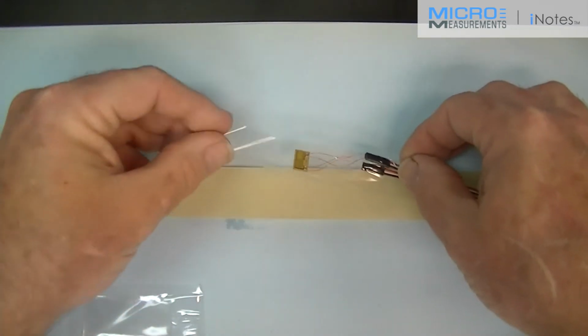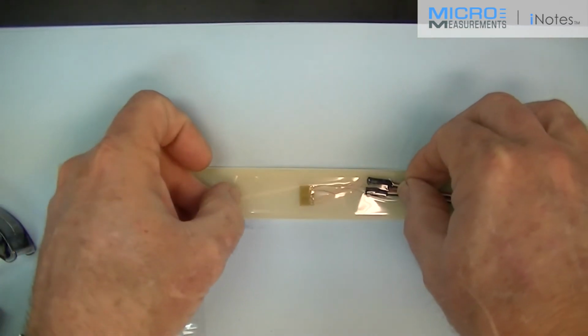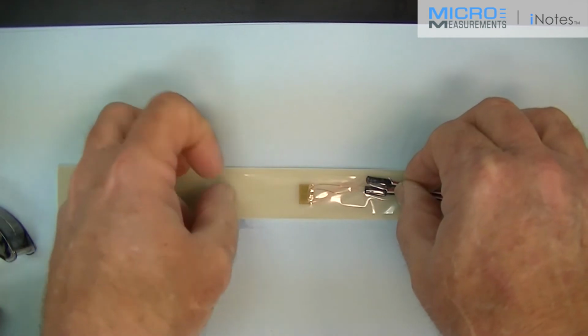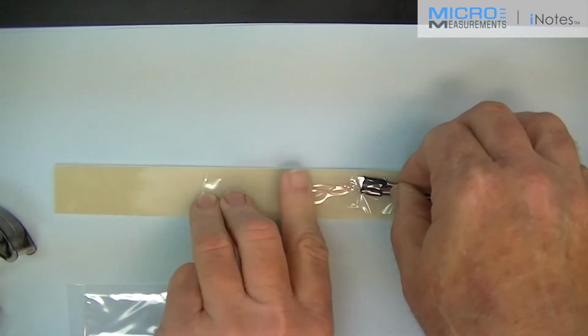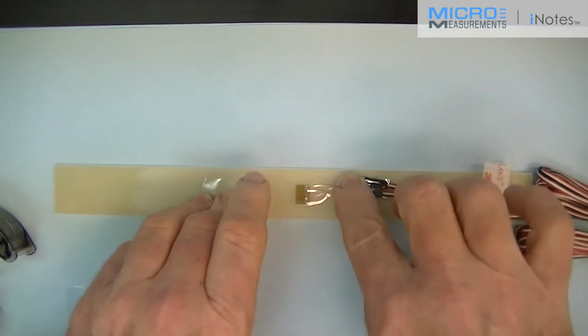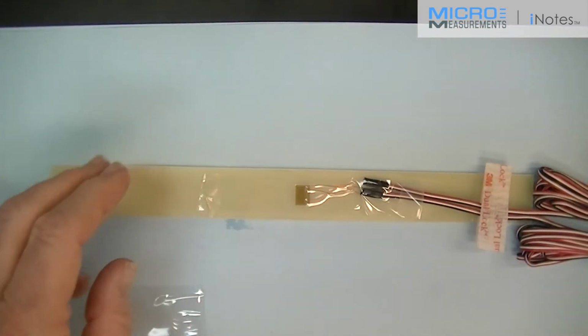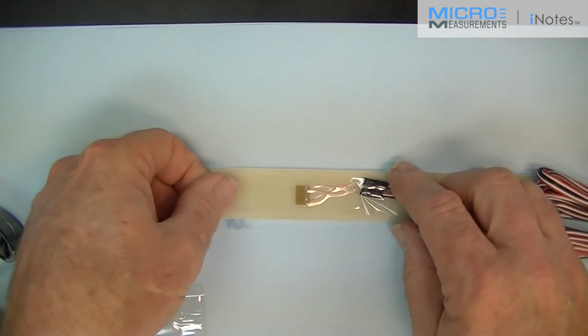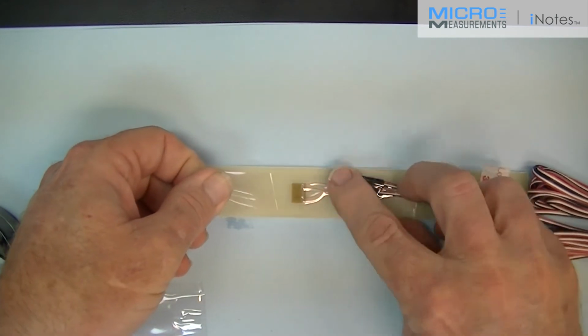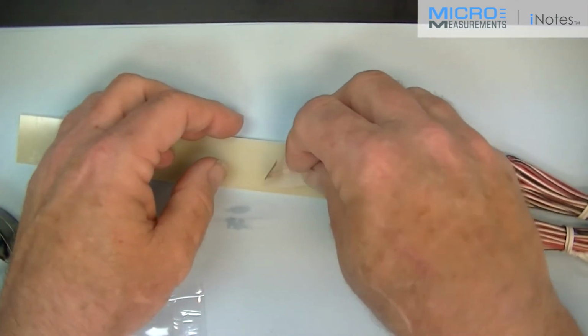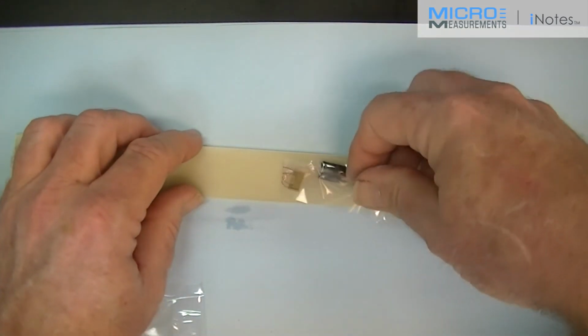I'm positioning it about midway between, because this is a standard coupon pull test. Alignment is not terribly critical. As long as you keep it straight, it's going to be straight. I'm then going to expose the bonding surface of the gauge, lifting at a shallow angle, and folding it back on itself.